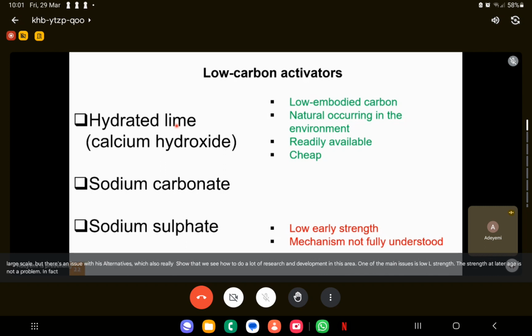In fact, when you use something like sodium carbonate to produce geopolymers, it has been found that it will give you approximately the same strength at 28 days compared to when you use sodium silicate and sodium hydroxide. But the problem is low early strength. So if I make a geopolymer with sodium carbonate, at 3 days I'll probably have like 1 MPa or 2 MPa, or my sample is even still soft. Whereas for the same mix, if I use sodium silicate and sodium hydroxide, it's probably almost 20 MPa. So that's one of the main challenges with low carbon activators right now, which really aims for us to find ways to improve the early strength when these kinds of activators are used.